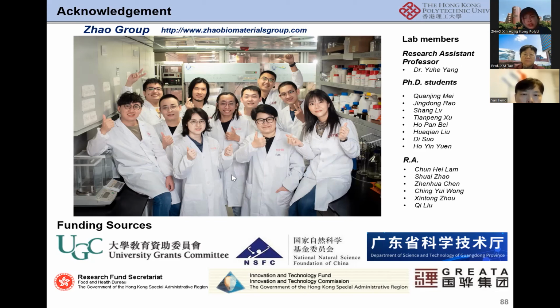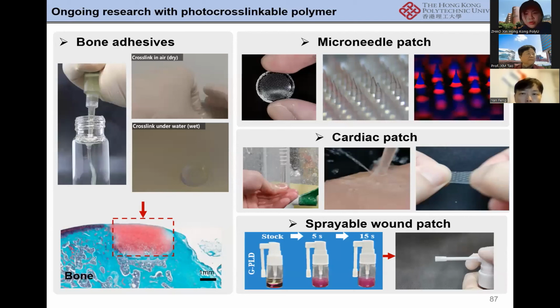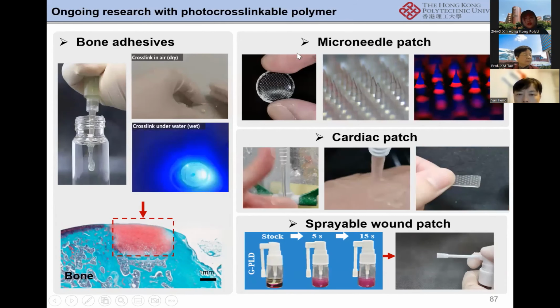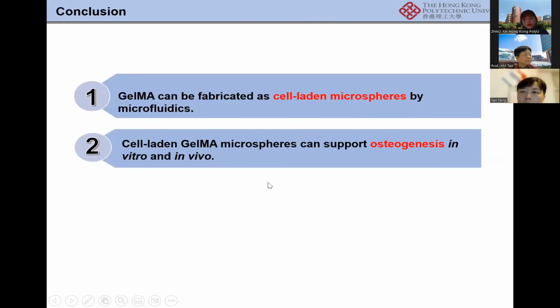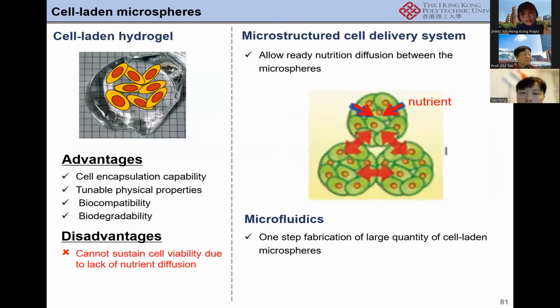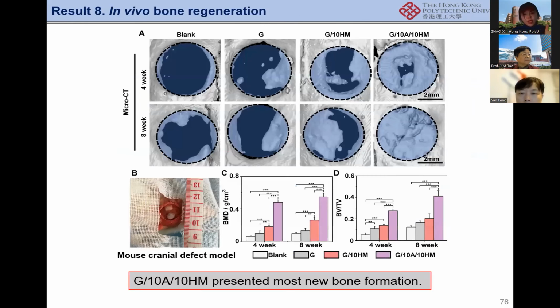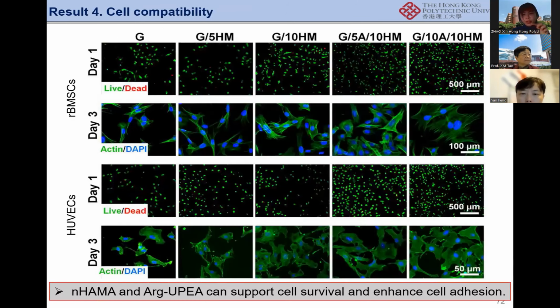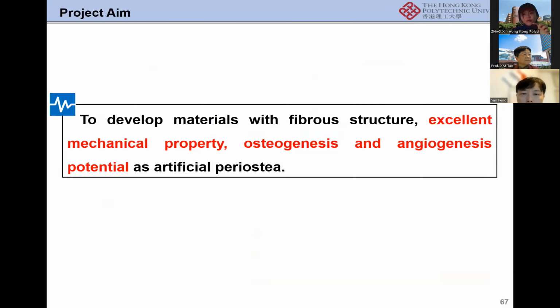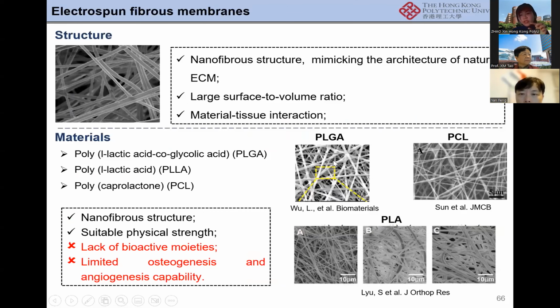So what we say is that it's not the electrospun fiber itself. If we just electrospin, for example, PLLA, the material itself is very stiff, and when we make the fibrous layer very thick, the pore size ends up very tiny, and the cells cannot penetrate.